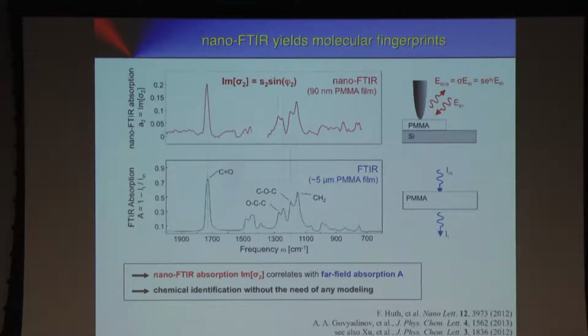And again, what we observe here is what we find empirically is that what we define as the nano-FTIR absorption, namely the imaginary part of the scattered field here, recorded as a function of frequency, it correlates with the far field absorbance, actually. And so we can directly compare. We don't need even to do modeling. Also, the scattering process is a rather difficult one. And so we can just take the spectra, go to a database, to literature, and we can immediately identify, well, this is PMMA. Again, I want to point out, this is a scattering experiment, and we measure absorption here.